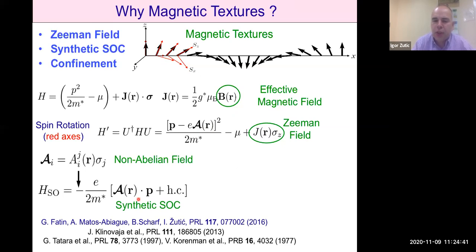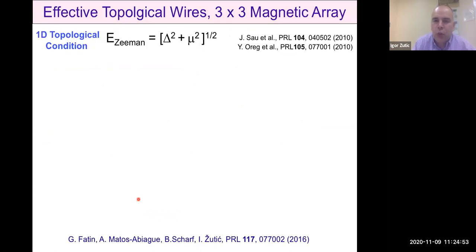So the presence of inhomogeneous magnetization can allow us to design spin orbit coupling that may be needed to support these Majorana fermions. To compare how our situation is different from a well-established one-dimensional case of these semiconductor nanowires, it's good to recall what is the characteristic condition for establishing topological superconductivity or establishing Majorana fermions. We need Zeeman splitting that is large enough, that is larger than this combination of superconducting gap and chemical potential.